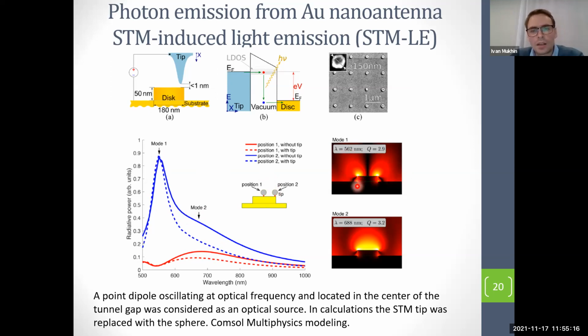And you can see that both modes have hotspots at the edge of the nanodisk. It means that the edge of the nanodisk will have enhanced local density of states. So remember these two modes. Then we start the experimental part of our work.